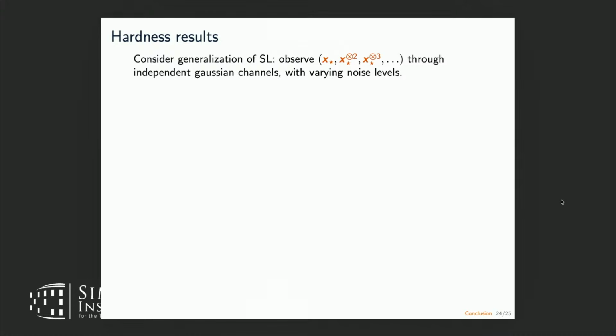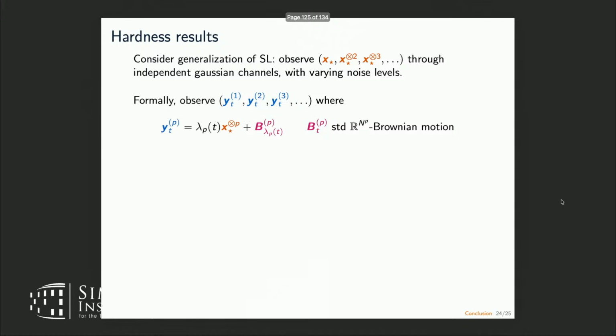I'll just mention one more result, which is on the opposite side of hardness. We can consider a generalized version of stochastic localization, and this will only make the algorithm stronger, and we show that even this will fail above beta stochastic localization. So in ordinary stochastic localization, nature samples x star from the target and then shows you a Gaussian channel observation of x star. In this generalized version, you'll also get to see Gaussian channel observations of various tensor powers of x star. So formally, you get to see a whole sequence of Brownian observations.